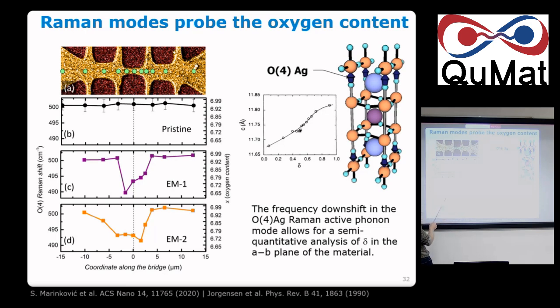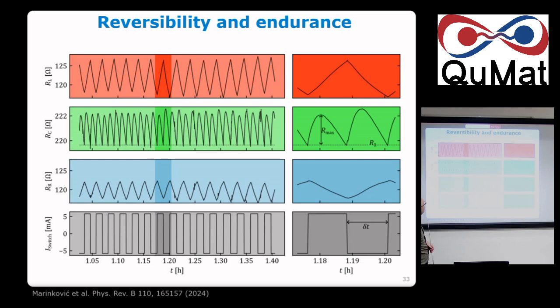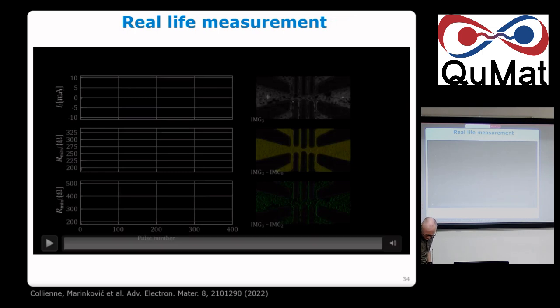Okay, if you keep electromigrating, you can propagate in one direction. And this, once again, you can do back and forth. So this is the same color code: blue on the right, red on the left, green in the center. And these are resistance as a function of the current, which is going positive and negative. So you're applying current, this. So you remove oxygens here, you put them there. So it goes down here, goes up here. And in the middle, you see that the wave goes through. So this is why you see a dome. And then you put them back on one side and the other. So you can put the oxygen one side, the other, one side, so you can do it more or less reversibly. I'll show you a small movie, perhaps, if that works.